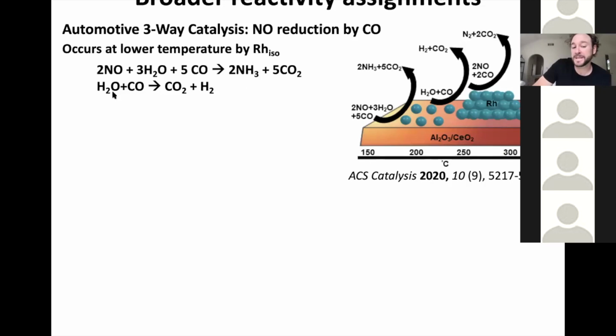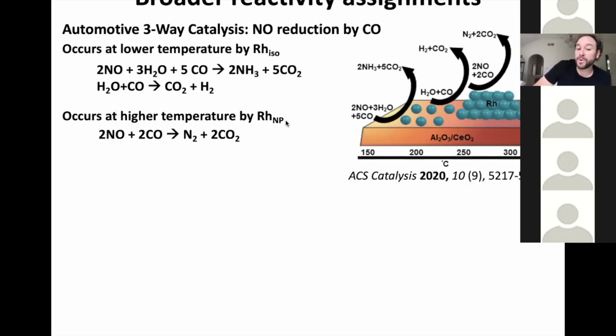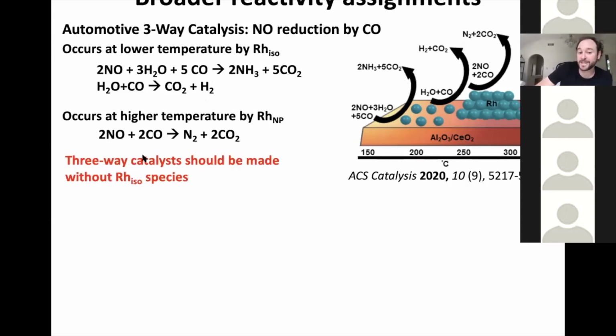And that's because they're particularly good at doing the water gas shift reaction, which makes hydrogen in situ. And this can work to hydrogenate NO and produce ammonia. On the other hand, rhodium nanoparticles do the chemistry you would like to do, which is NO reacting with CO to form dinitrogen, which is the species we would most like to emit from the back of our car. So this told us that three-way catalysts should be made without atomically dispersed rhodium species. So this is to say these sorts of materials, single atom catalysts, these atomically dispersed metal catalysts, are not great for everything. They have distinct selectivity here compared to clusters, but not in a way we would like.